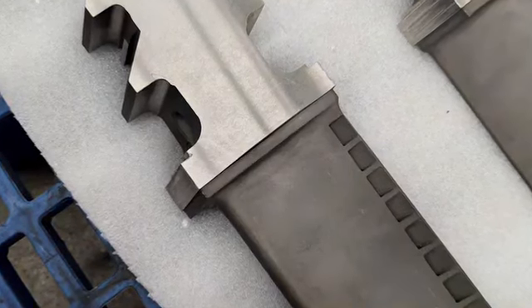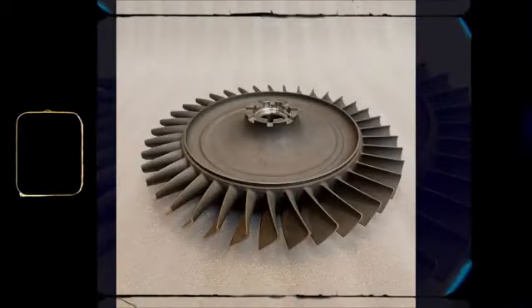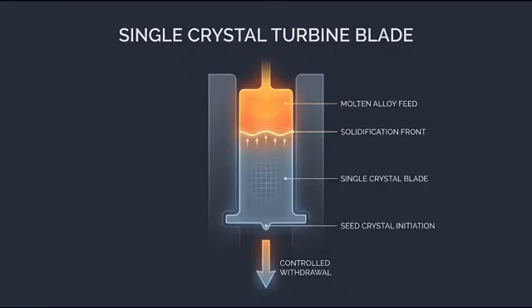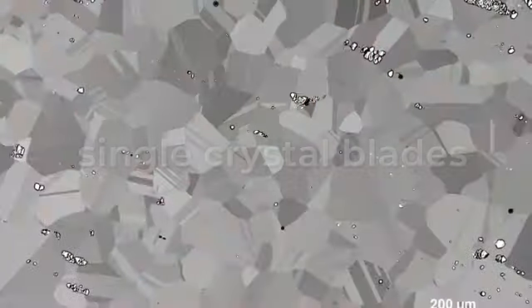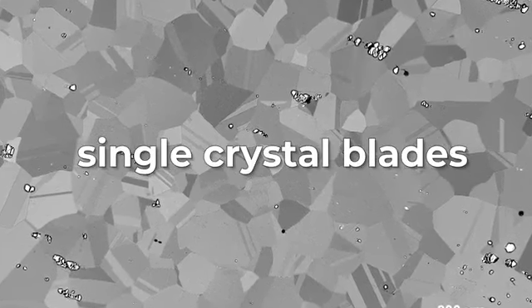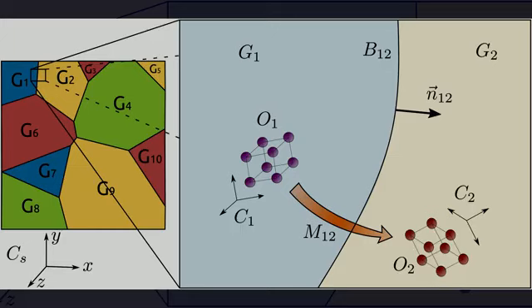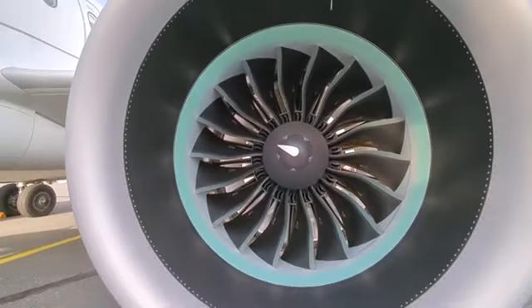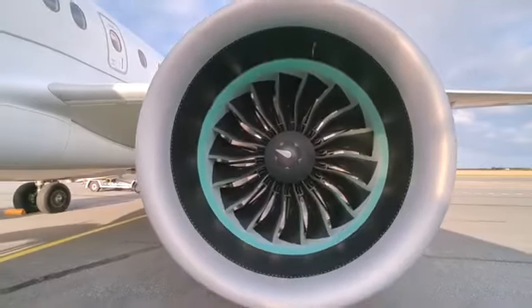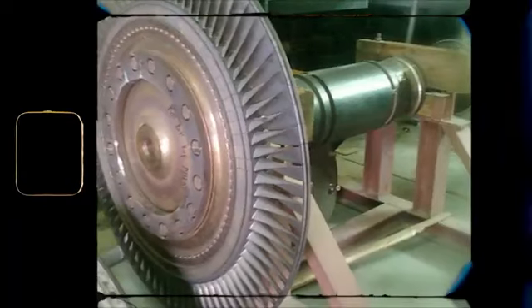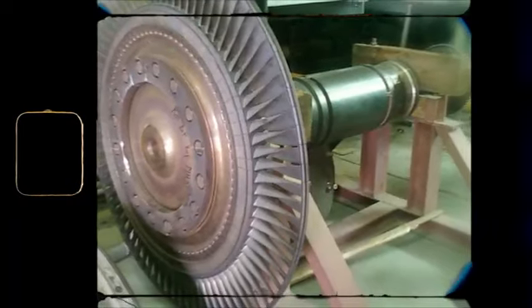They want the entire blade to become a single crystal of metal, growing from one seed point upward through the mold. Single crystal blades have no grain boundaries, the microscopic seams where crystals meet inside a metal. Grain boundaries are weak points under cyclic stress. Under the stress of a spinning turbine, they propagate cracks. Remove them entirely and the blade becomes far more resistant to the forces trying to tear it apart at 10,000 revolutions per minute.